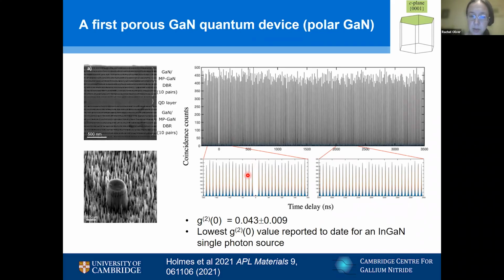Zooming in here on the dip, we can see that using this cavity structure in this micropillar, our dip is down to 4%, rather than some of the ones I showed earlier at 40% of the surrounding peaks. And this we think is the lowest value of that dip that's been reported to date for an InGaN single photon source. It's arising because we have very good light extraction using the distributed Bragg reflectors. That enables us to change the pump regime and really just tickle the dot rather than exciting the surrounding quantum well. So the DBRs are really enabling us to access this much cleaner, more spectrally pure region of emission.